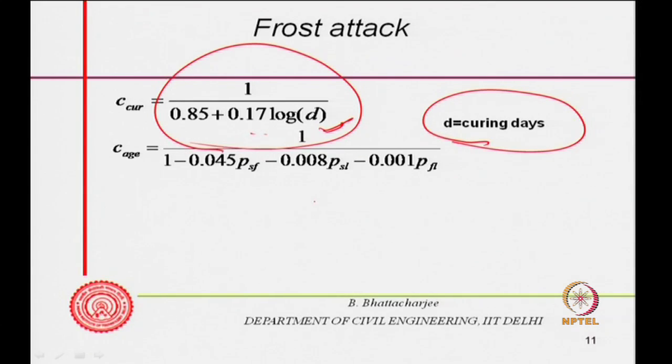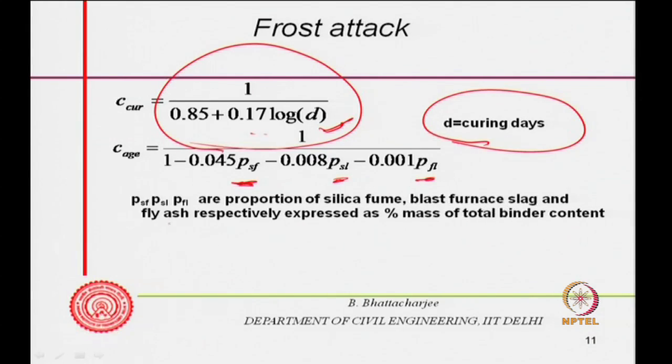C age: if the age is more, obviously this value should be less, but this will also depend upon the supplementary cementitious material or pozzolanic material that you are using. For example, P_SF, P_slag and P_FA are the proportions of silica fume, blast furnace slag and fly ash respectively, expressed as percentage of mass of total binder content. So, if you use slag, fly ash and silica fume, this effect of age will be less, because this value will be large, so this tends to be a smaller value, 1 minus this higher value gives a smaller value. So, this will become 1 minus this, so this will become larger,